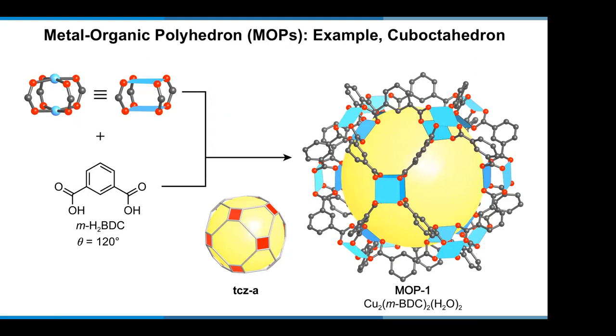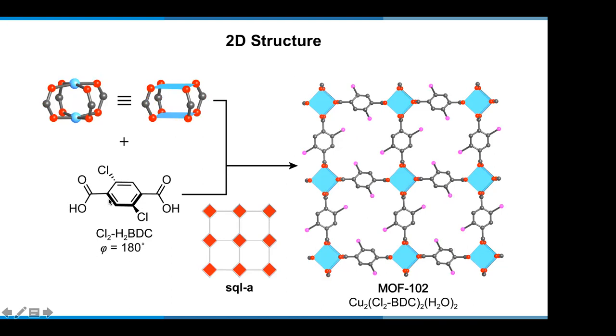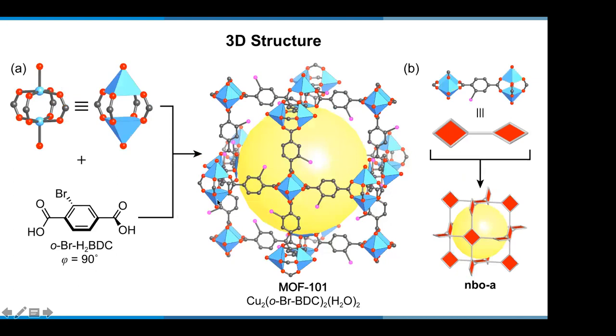The particle itself is porous. And now you can also play with this angle at 70 degrees to get the ladder arrangement. Or when the carboxylates are at 180 degrees, you get the square grid. These carboxylates are on the same plane, so the squares are on the same plane. And if you don't want to make a 2D or a 1D, you put a bromo functionality here to keep these carboxylates at 90 degrees to each other. And when you run this reaction, if you don't heat up the reaction, then these angles will be maintained. And in the end, it puts the squares at 90 degrees to each other,